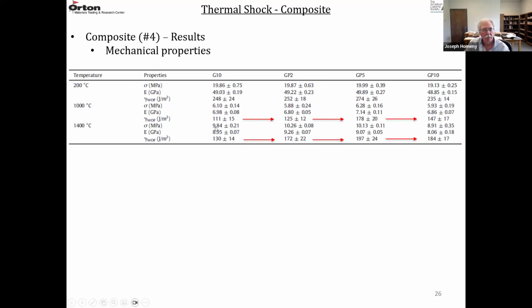And when you coke it at a little bit higher temperature, 1400 degrees C, the strength starts to go up again, 9 to 10 MPa. The modulus goes up slightly, maybe around 9 GPa, because of the sintering effect. And then the work of fracture is still lower than at 200 degrees C, but it is increasing again from left to right as you add more of the pellets.